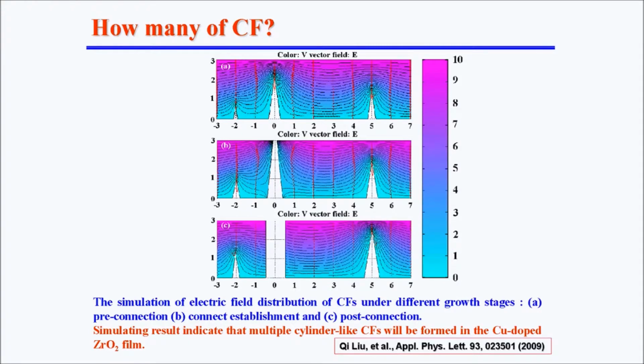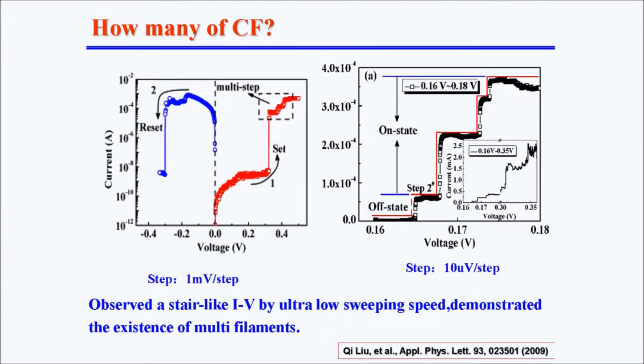Before we do some of the simulations, we can see usually the switching layer is an insulating material. There are a lot of defects. When it's stressed, at the highest electric field area it's easier to form the filaments. Then if the stress increases the electric field, another filament will form. That means basically they can form multiple filaments. Then we try to confirm it with experiments here. We can see both in the set process and the reset process, they are not abrupt processes. They have a step-like process. If you further slow down this process, we can very clearly see the step-like behaviors.